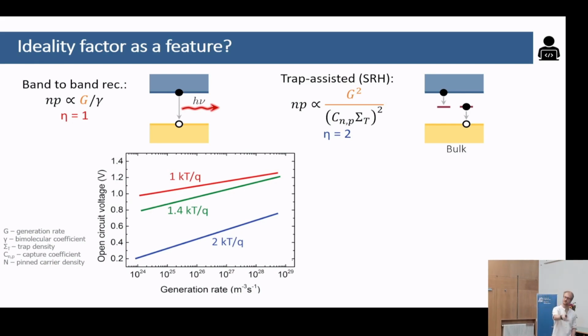So as a feature, because you need to go slightly beyond just giving it a VOC, short circuit, and fill factor, one of the ones that was very natural to distinguish the different kinds of recombination was the ideality factor, which is the slope of the light intensity dependence versus the VOC, on a log-lin scale. And basically, you can derive some equations, and if that slope is close to 1, it should ideally be purely band-to-band recombination or bimolecular recombination. And if it's close to 2, then you're dominated by trap-assisted recombination.